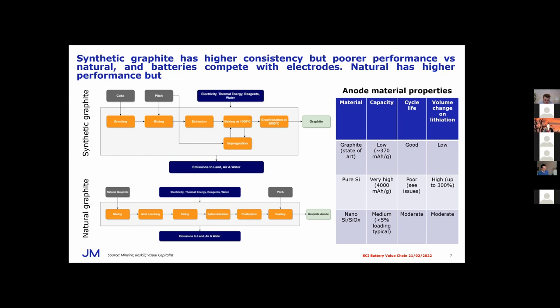Unfortunately, it's very difficult to create the sort of pressure and temperature environment in which natural graphite forms. So generally synthetic graphite does tend to be more consistent and homogeneous, but lacks the flake composition that we see for natural graphite. So it performs, but generally doesn't perform quite as well as natural graphite in lithium-ion batteries.